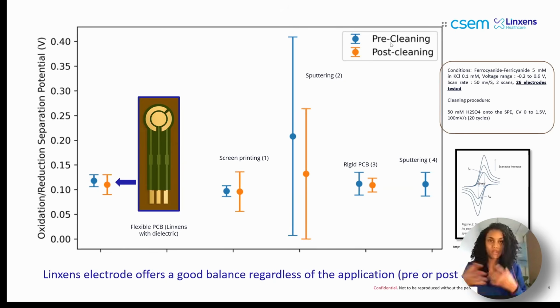And I think thanks to this technique, we are able to produce a deposition of gold with a good density, and thanks to that, you don't have this pin. But we have some limitation on the usage of our electrodes. We cannot go up to 1 volt in a chloride media because, as you said, we can have the risk where sometimes, if there is some copper, this copper can react with our electrodes.